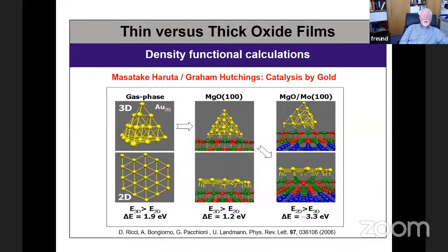However, the authors of the cited paper here showed that, in fact, when you put the gold particle not on a bulk MgO, but rather on a thin film, like two monolayers of magnesium oxide, the three-dimensional structure collapses and forms a flat pancake. And that flat pancake comes about because electrons are tunneling through the thin film. And since gold is one of the most electronegative metal systems, almost as electronegative as the halogens,